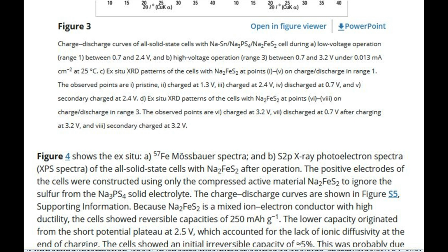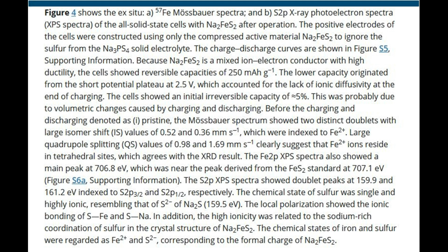Figure 4 shows the ex situ, a, 57Fe Mossbauer spectra, and b, S 2p X-ray photoelectron spectra, XPS spectra, of the all solid-state cells with Na2FeS2 after operation. The positive electrodes of the cells were constructed using only the compressed active material Na2FeS2 to ignore the sulfur from the Na3PS4 solid electrolyte. The charge-discharge curves are shown in figure S5, supporting information. Because Na2FeS2 is a mixed ion electron conductor with high ductility, the cells showed reversible capacities of 250 mAh g-1.